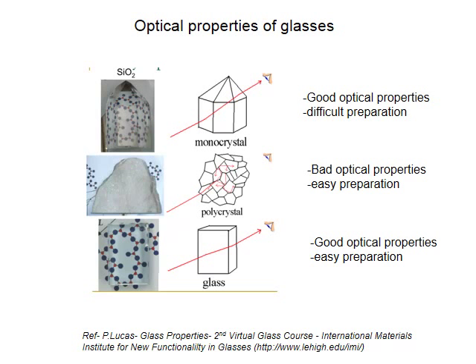A monocrystal will have optical properties defined mainly by the optical constants. Optical quality is good, but they are difficult to prepare. Polycrystalline insulators have microstructure that can have additional effects on transparency. If multiple phases are present, or in the presence of grain boundaries within a single phase, strong scattering processes may occur from any region with a sharp change in refractive index, and this scattering makes the insulator opaque. Another source of opacity in insulators can come from dopants that absorb light through bound electron excitation. Transition metal and lanthanide oxides are important examples of such absorbing species, and they add color to insulators.